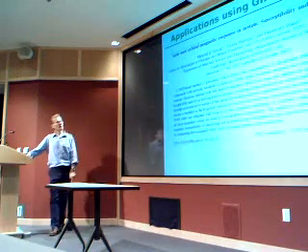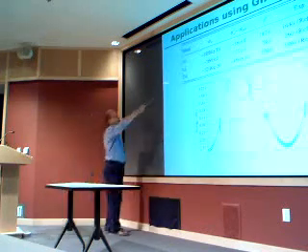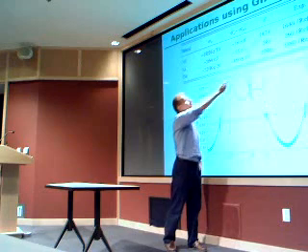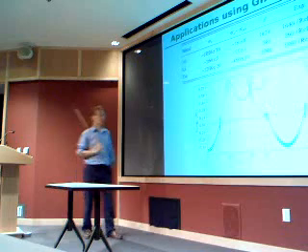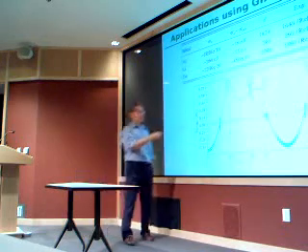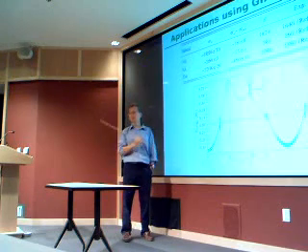Then I mentioned the metals. I just quickly show some results. So first for two simple metals, and copper is also quite simple. If you calculate the chemical shift and compare to experiment, one is not that close, but within, let's say, 10-20%, one can reproduce the values. And then this is not a quantitative value, but this is the contribution of the different parts of the band structure of this lithium for the Knight shift.